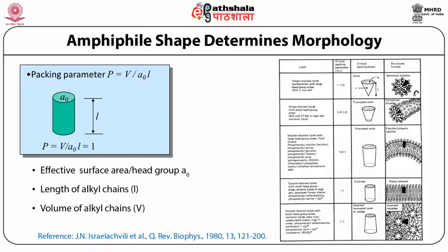But if you increase the salt amount in the SDS micelle, the head group area effectively becomes small because of the charge screening of the repulsive force. In that case, the critical packing parameter increases and lies between 0.33 and 0.5, and the critical packing shape becomes a truncated cone and can eventually form elongated cylindrical micelles or worm-like micelles.